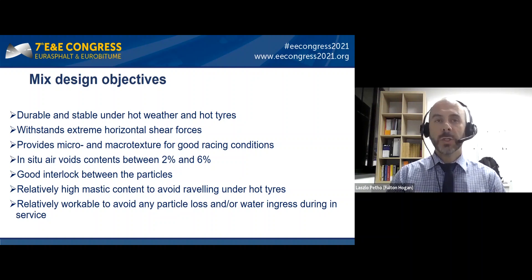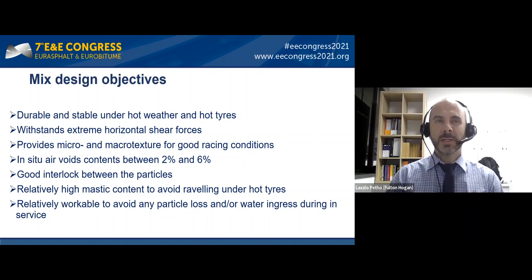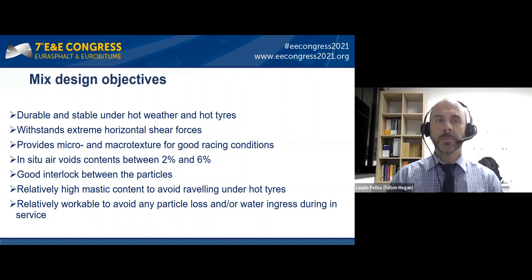The in-situ air void content had to be low: two to six percent. As you can gauge, this is a fairly low air void content for road conditions, so we had to keep in mind that rutting shouldn't be an issue and we had to provide good interlock between the particles to avoid loss of aggregates.